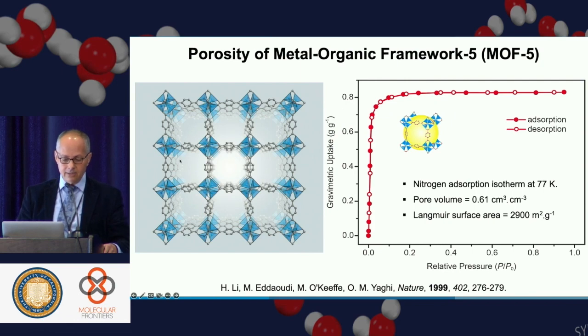The structure looks like this. It's infinitely extended. And the isotherm is shown here. Type 1 isotherm, showing that, in fact, it remains open in the absence of guests, and the pore volume was 61% of the entire crystal, 61% by volume. And the Langmuir surface area that you get from these nitrogen adsorption isotherms, at the time we calculated to be 2,900 meters squared per gram. When we reported this, everybody paid attention because this broke all records of porosity that preceded MOFs, with zeolites and porous carbon and other materials.